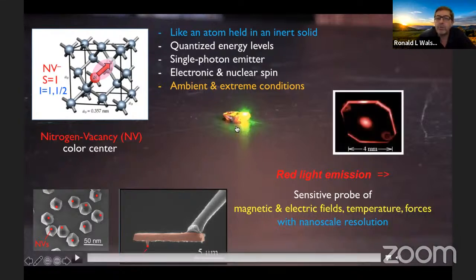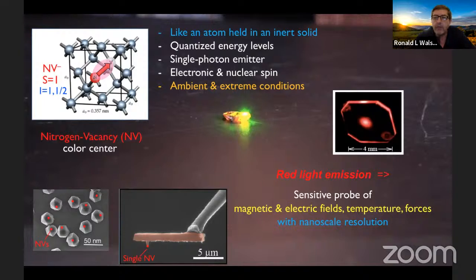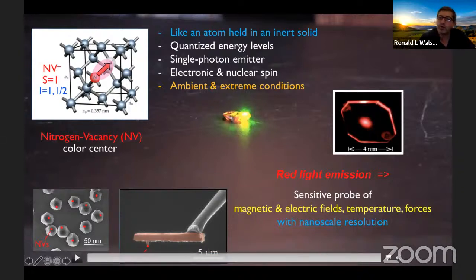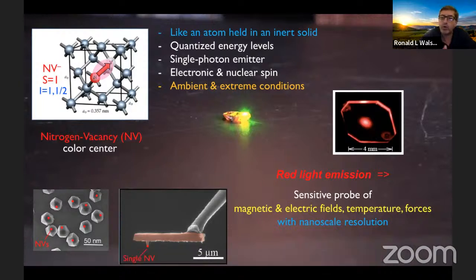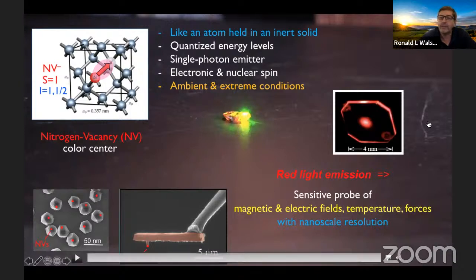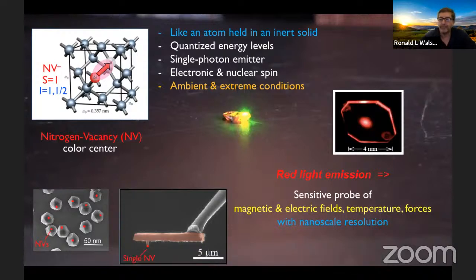Sometimes, like in this movie of the chunk of diamond or in this image here, you may use a macroscopic diamond that's filled with many NVs, an ensemble of them. The more NVs you have, the more signal you get and the better sensitivity of the sensor you have. Although you'd lose spatial resolution, you just have a bulk sensor. You can also have the NVs just grown at the surface layer of a bulk diamond and use it for wide field imaging and microscopy. And I will talk a great deal about that as we move forward.